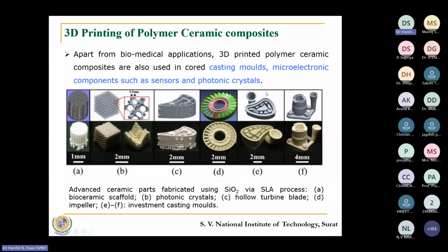But apart from that, people also have reported 3D printing of polymer ceramic composites to be used in casting molds, MEMS for making sensors, and photonic crystals. You can see the size of these parts. You can see that these are different parts which are attempted by mixing silicon oxide into resin, so that through SLA you are able to create a part. Here you can see that this is a bioceramic scaffold. You can also see a photonic crystal, hollow turbine blades. You can see the size. Impellers have been attempted, and various micro investment casting molds have also been attempted with reasonably good accuracy, dimensional as well as form accuracy.